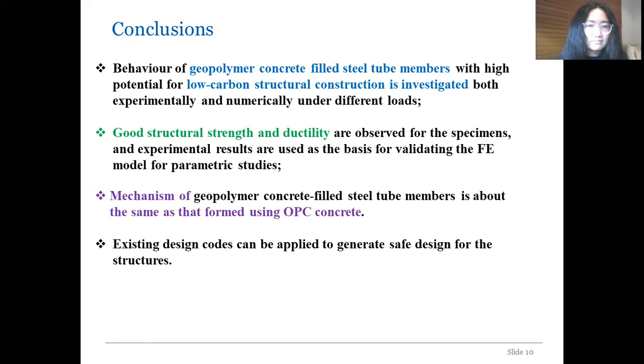So finally, I wish to draw the conclusions. This research mainly investigates the behavior of geopolymer concrete filled circular steel tube members with high potential for low carbon structure construction to reduce the environmental impacts due to structural construction. Good structural strength and ductility are observed for the structures, and the experimental results are used as the basis for validating the FE model for subsequent systematic parametric studies. The mechanism of the structures was investigated and found to be about the same as that for the conventional structures with the infill of ordinary Portland cement concrete.